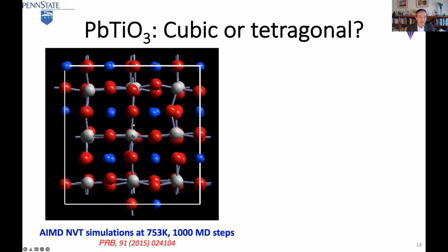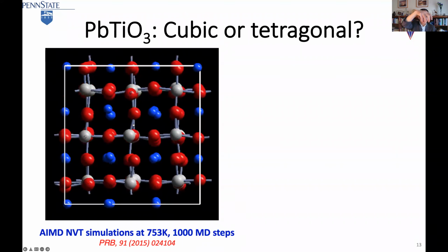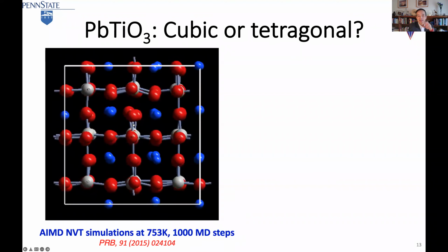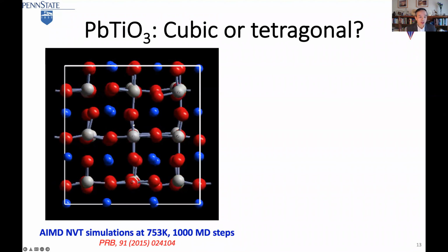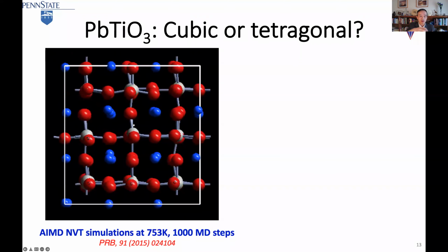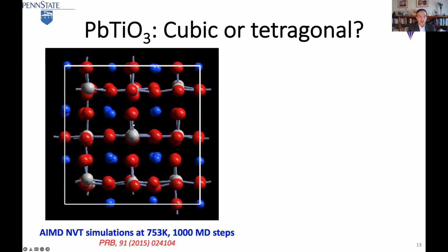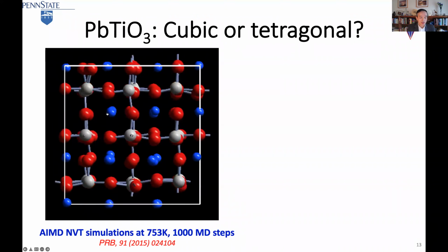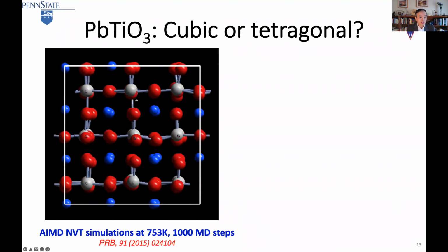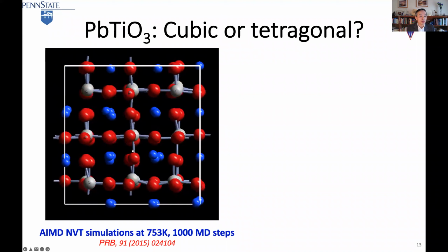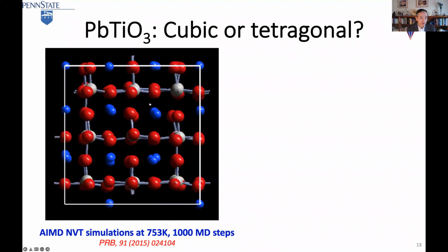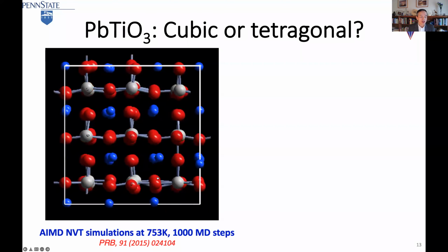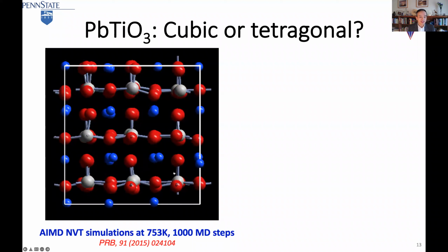So what actually happens is that if you think about this as the c-axis, it goes like this, and then it goes like that, and it goes like this. So the c-axis of the local titanium atom in the unit cell goes to the z direction, then it goes to the x direction, and goes to the y direction. Now when this switching happens, if a neighbor does not switch, then you create a kind of domain wall between these 2 unit cells, or between two rows of them, or in that direction. So in all 3 directions, you create domain walls. That's exactly what happened.